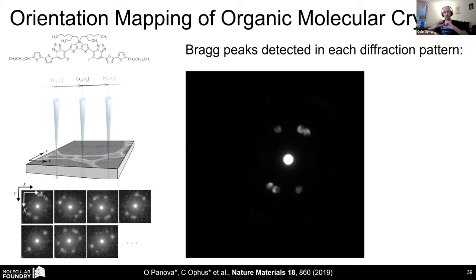Some of our experiments with 0.1 milliradians, 100 microradian semi-angle, are basically just like conventional selected area diffraction. You have a very parallel electron beam. Whereas if you push the convergent semi-angle out to 4 milliradians, almost touching, the tails of your probe will reach out about plus or minus 1.5, 2 unit cells of the material. And if you want subatomic resolution, you can push your probe down to an angstrom, half an angstrom, something on that scale. The flexibility, the tunability of being able to set the convergent semi-angle is one of our key advantages.